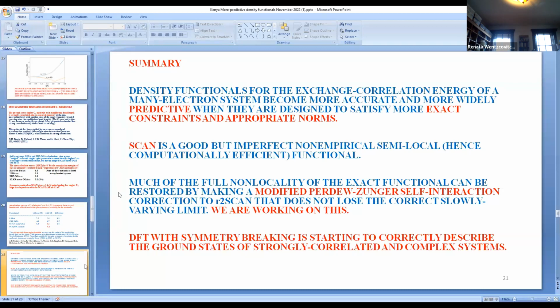SCAN is a good but imperfect, non-empirical, semi-local, and hence computationally efficient functional. Much of the full non-locality of the exact functional can be restored by making a self-interaction correction. I told you that in strongly correlated systems, one needs a self-interaction correction. Plus U is often interpreted as an effective self-interaction correction, but I think one needs to make a real self-interaction correction by a modified Perdew-Zunger self-interaction correction.